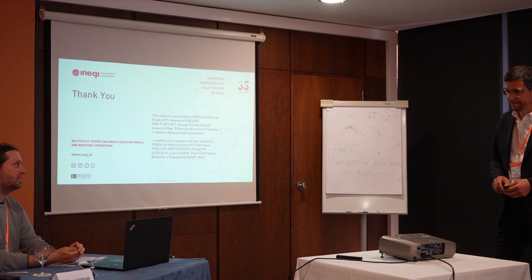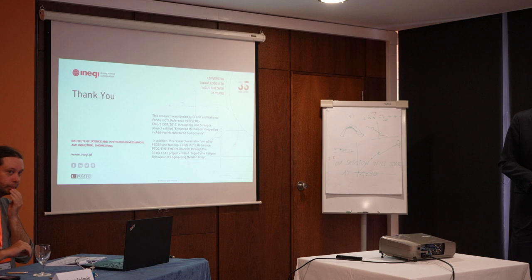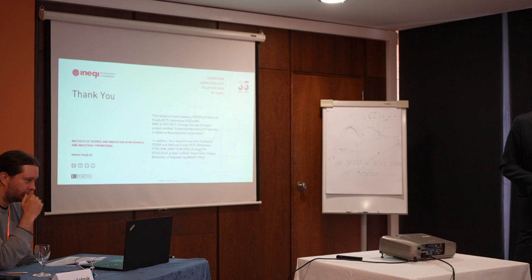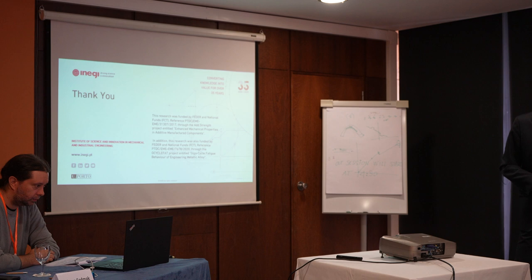Thank you for your presentation. Do we have any questions? I think this is more of a comment. Using CT specimen geometry, which we have used for years in conventional manufacturing to apply information to components like an aircraft wing — additive manufacturing is not meant for those situations. In additive manufacturing, it is more of a 3D geometry where small crack growth controls life. Therefore, the region of interest in crack growth is really the threshold region, not the long crack region. When you go to the threshold region, you will see effects like surface roughness, defects, and residual stresses — all of those small details show up there, and that is really the region of interest in many additive manufacturing applications.